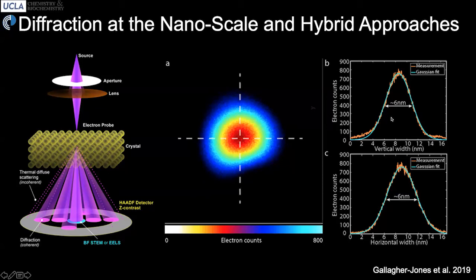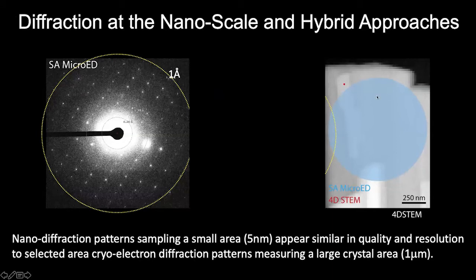In this case, you can see a profile of a beam that's only about 6 nanometers in full width at half max to try and illuminate very small regions of a crystal. And just to illustrate what that means, I'll show you a picture of a crystal here in the background and a conventional illuminated area using microelectron diffraction techniques in blue. And here you're illuminating a good portion of the crystal.